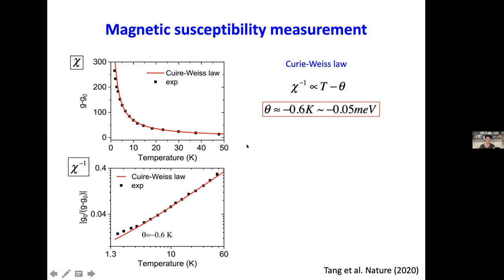We use the difference between left and right circular polarized light under magnetic fields, and then look at the slope. So this is the chi we measured as a function of temperature, and 1 over chi fit. So we got a Weiss temperature on the order of -1 Kelvin.